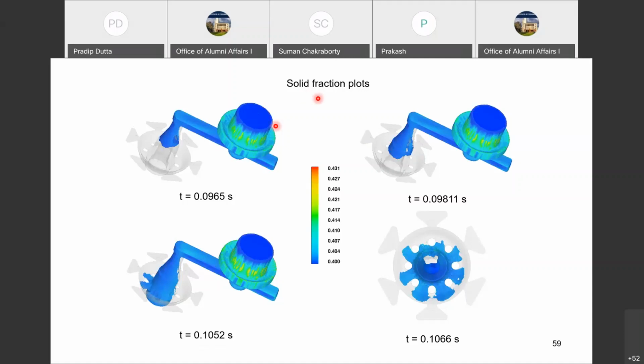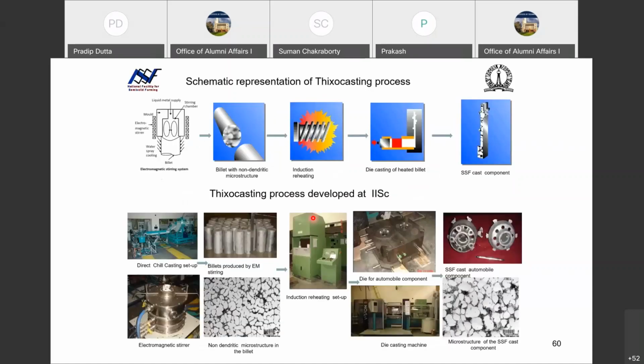We are looking at the solid fraction plots, right? So finally we do the CFD modeling, and then we produce the parts in the die casting machine. Our die casting machine is shown here, which is a Buhler die casting machine. And the journey here is that we start with electromagnetic stirring, then billet production. These are schematically shown here: induction reheating, die casting, and then the final part.